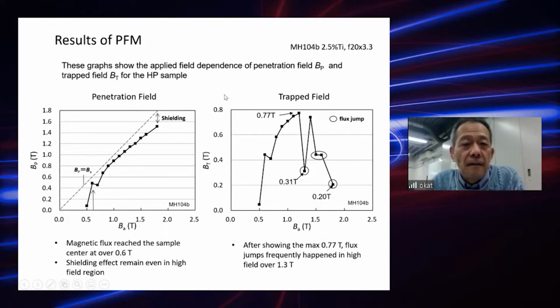So these are the results of the PFM. MH104 means the sample from Dresden. This graph shows the applied field dependence of the penetration field BP and the trapped field BT for the hot pressed sample. The magnetic flux reached the sample center at over 0.6 Tesla application. The shielding effect was kept even in the higher applied field region like this.